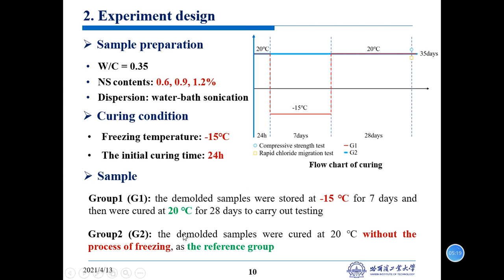And the other one, we want to use this sample to simulate concrete under construction, exposed to weather such as cold waves or snowstorms. Another one is curing at 20 degree. We can see this sample is without the process of freezing, as the reference group, to explore the effect of early age frost damage on the cement paste.